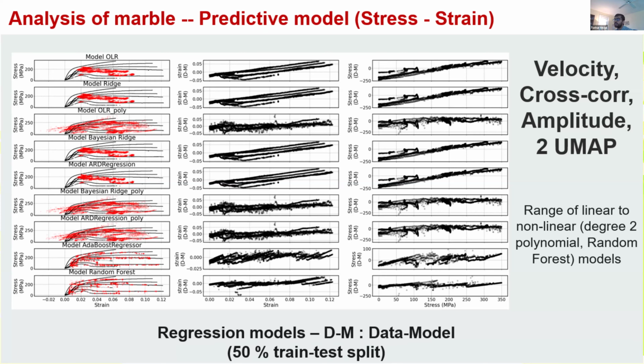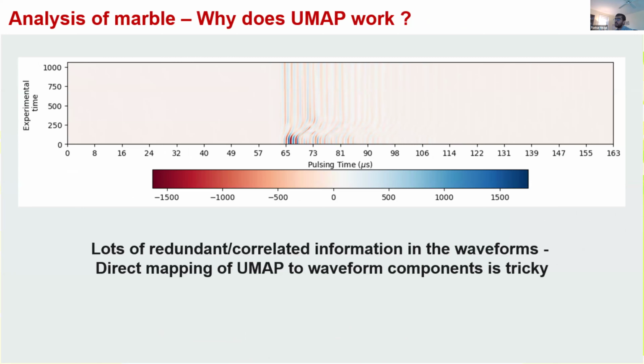So overall, we found this was pretty promising, showing that adding some information from the structure of the waveform can be really important in improving the prediction of where we are with regards to the rheological state. But we wanted to push this a little bit further and ask, why does UMAP work? What are the aspects of the waveform that it's actually using? One could ask which exact parts of the waveform UMAP is using. The challenge with UMAP is that it's very good at nonlinear dimensionality reduction, but it's very nonlinear. As a result, it doesn't have a clear sensitivity, so you can't go in and say this time step in the waveform is what it used.